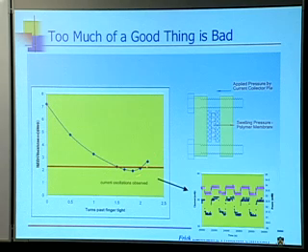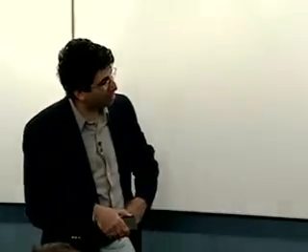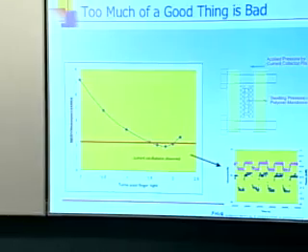Now, right here on this critical point, what's happening, you've got just enough of a gap here and spacing so that the water can start to be generated. The material will swell. It first optimizes. You get a nice current flowing as the membrane and electrode interface optimizes. And as it optimizes, you have more current. And as a result, you have more water. And now you're pushing too hard against the electrodes, and the water is coming out because there's not enough space there. And so the structure collapses on you, and you go into these oscillations. And so these are actually steady states at the top and at the bottom here associated with the cell.